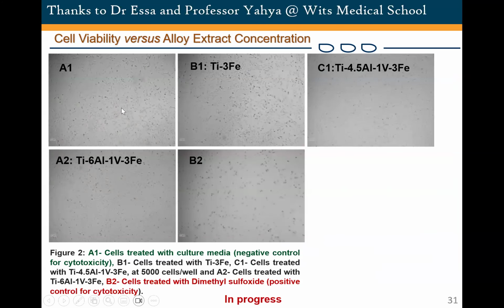And when you use the alloy extract, what you find is, are you finding situations that are consistent with positive control or situations that are consistent with negative control? They were able to quantify the cells, and the quantification is represented in terms of cell viability. So there is 100% concentration of the extract, then they diluted it to 50% as well. The dilution should be closer to what you would experience in the human body because, of course, the fluids are constantly flowing; they are not stagnant.